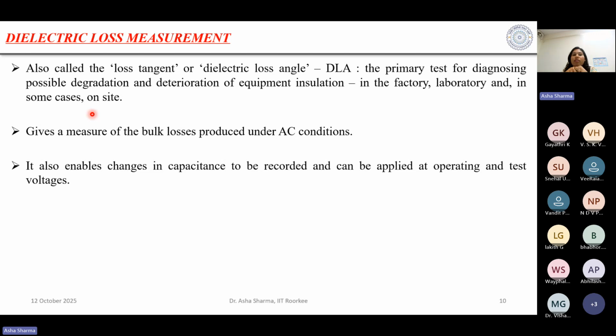This is a primary test for diagnosing possible degradation. Means if the R is very low, we will say the material has been degraded, and the equipment insulation has deteriorated. This dielectric loss measurement can be done in the factory, in the laboratory, or on-site as condition monitoring. It gives a measure of the bulk losses produced under AC conditions, and these are losses which we don't want. It also enables changes in the capacitance to be recorded and can be applied at operating and test voltage. We are also able to measure the capacitance as well.